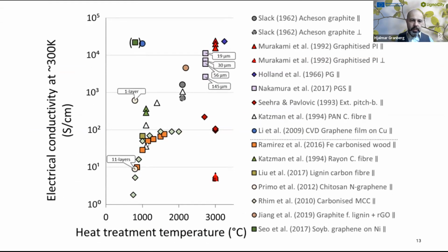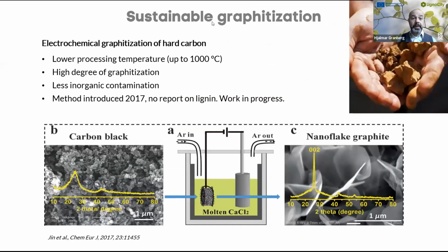And here is a review of what has been done before. So with increasing heat treatment, you usually can end up with more pure graphitic structure, like here, but you can also fail and end up here. When it comes to biomass, you usually focus on the low temperature materials, since it's not considered optimal for graphitization. But now things are opening up. So these low temperature, everything below 1000 degrees is considered low temperature, uses then less energy, and perhaps you can obtain these extreme values. For example, producing this based on the electrochemical graphitization method.